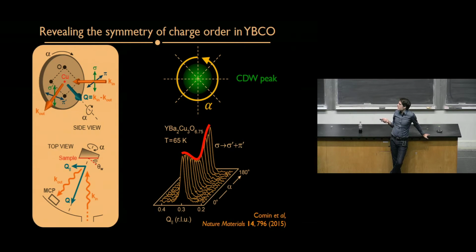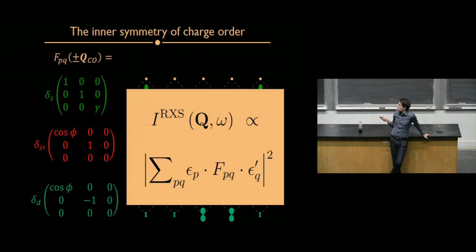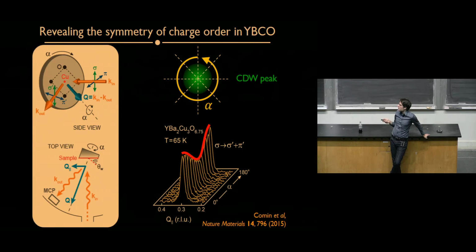And we did this measurement. The way we do it actually is we rotate the polarization around the crystallographic axis, and then we measure how much the signal changes as we rotate the incoming polarization. Unfortunately, we cannot yet control or measure the outgoing polarization, but we're in the stage of developing tools to do that. But what we can do is rotate the incoming polarization and basically project different components of these tensors and then look at how the total signal is modulated in intensity.